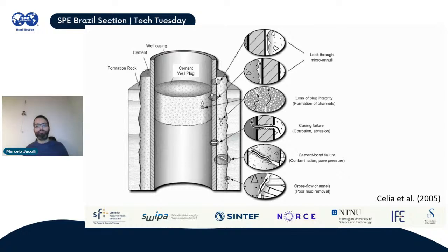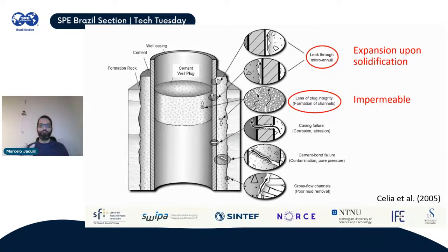The concerns regarding cement can be summarized through this figure. This figure has become really popular in well P&A articles because everyone refers to it. It's very good at pointing out the leak paths. If you consider a well abandoned with a cement plug, there are several potential leak paths: across the plug, between the plug and pipe, between the pipe and the cement behind it, or between it and the formation. But specifically regarding the plug, our main concern is on these two potential leak paths.